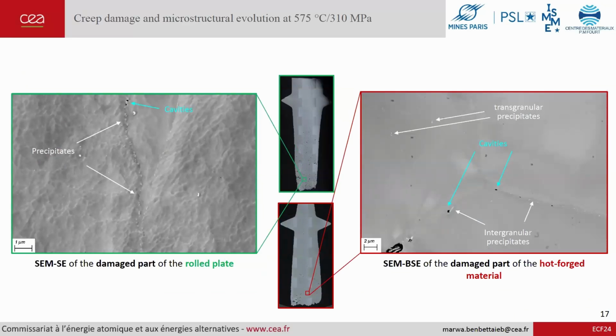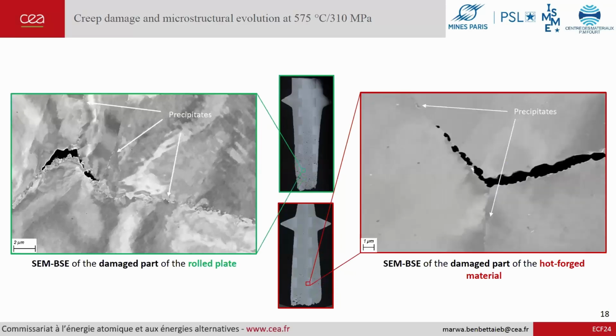Let's now take a look at the microstructural evolution of the tested specimens. We can note for the two alloys the presence of intergranular precipitates, and the precipitates for the niobium-free alloy are identified through the literature as probably M23C6. And we can note the presence also of transgranular precipitates for the niobium-rich alloy. And in both cases, we can see here that the cavities initiate from the intergranular precipitates, and that the crack initiation then is intergranular for both cases.